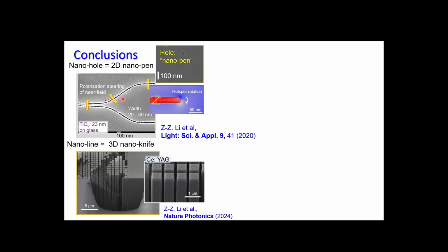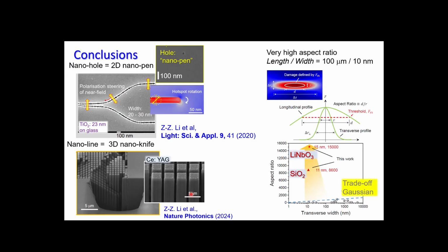So what I showed is that we can use a femtosecond laser beam for the task, which would be femtosecond laser lithography down to resolutions of tens of nanometers. Then using similar physics, light is localized on the nanoscale, and modification can happen down to tens of nanometers, which later you can use for etching structures out. So this is an example of how you fabricate some volumetric structures with this 3D nanoscale technology with very high aspect ratio. So we know that if we are working at the threshold, if the lateral resolution is small, it will also make the axial resolution smaller, so they are somehow linked.